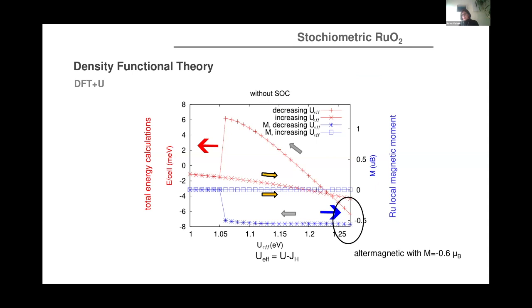However, if you go now to smaller U's, this solution very fast is in fact unfavorable, and the favored solution is the one with no magnetism. So now one could say, okay, one observes this altermagnetic order in the calculations. However, these values of U effective, this 1.25, is extremely large for ruthenium, for the transition metal ion.